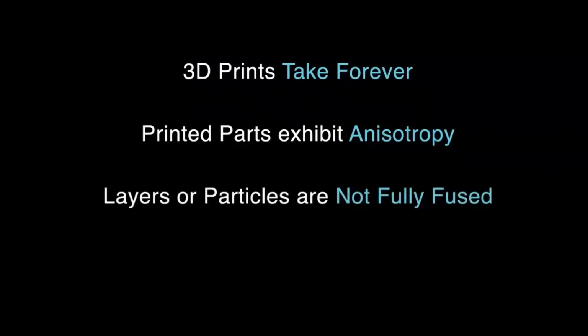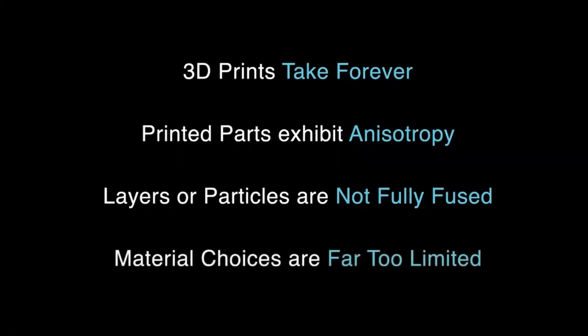Those layers, or if it's a powder fusion technology, they're not fully fused, especially for polymers, where the properties of a polymer are all derived from chain entanglements. Relying on quiescent diffusion without any convection doesn't give rise to the full envelope of entanglements that you like to have between particles or layers under traditional manufacturing. And the material choices have been far too limited.